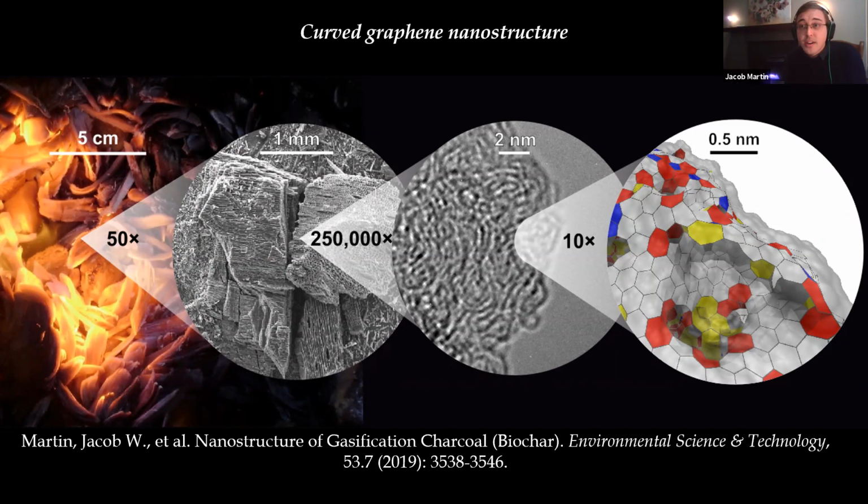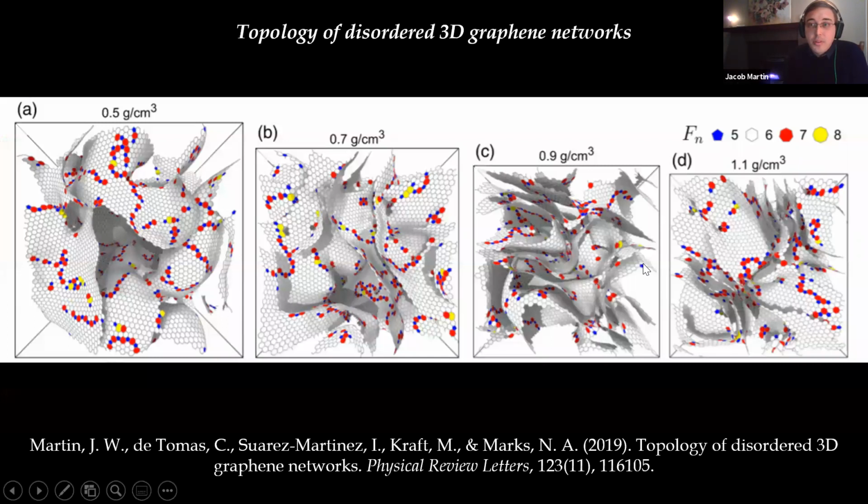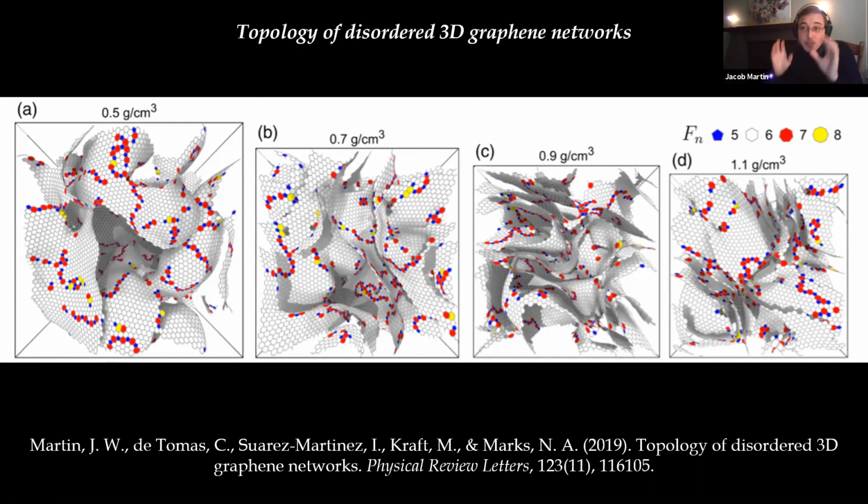But we wanted to go further than that and simulate some much larger structures. And there was a group, the carbon group at Curtin University in Perth, that had previously simulated some of the largest structures. And at a conference, we talked about how to analyze these, and so this is the next bit of work we did. These are some of the largest structures of disordered carbon that have been prepared using a reactive force field. So we literally just place the atoms inside the box randomly and allow the reactive force field to break and form bonds, and these structures emerged completely randomly.